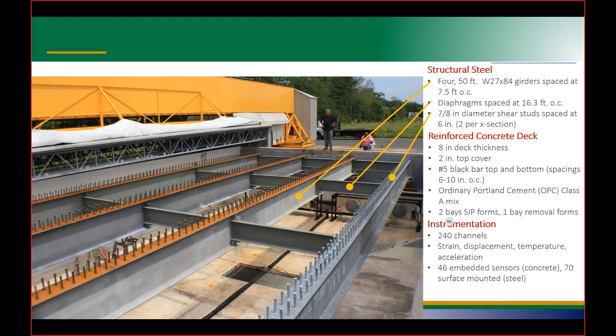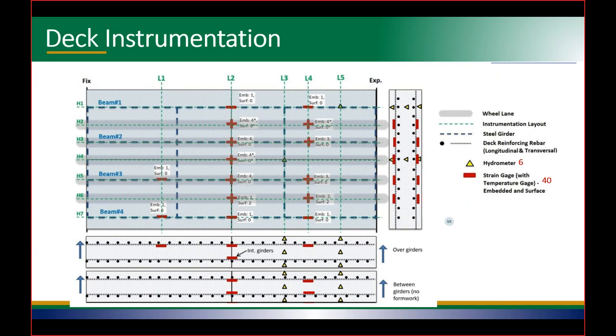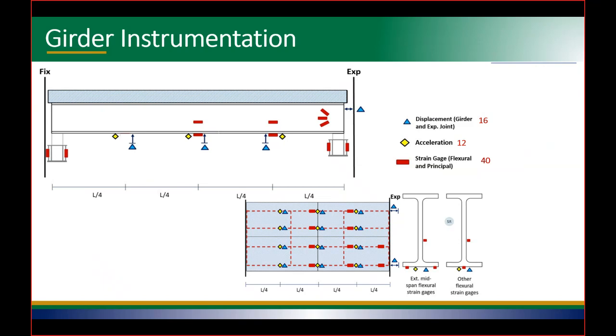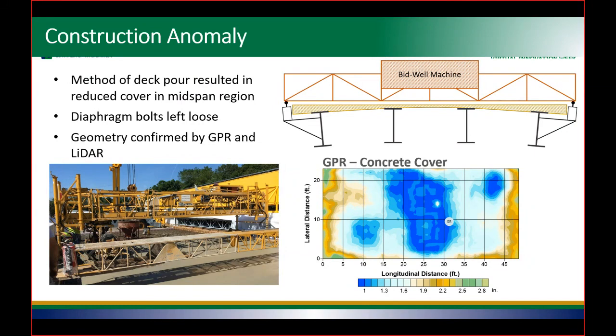We also installed a full fixed instrumentation system. That included 40 strain gauges embedded in the deck. Each strain gauge also included a temperature gauge, a thermistor, and those gauges were tied alongside the longitudinal and transverse rebar and at different depths to provide a full characterization of the strain profile in any given section. The steel girders also had strain gauges, again, to better characterize the cross-sectional strain profile, and also to locate neutral axes. And then we had strain gauge rosettes at the ends of two of the girders to better characterize shear strain, and strain gauges in the pedestals to capture the entire load presented to the structure. And then displacement gauges and acceleration gauges distributed at quarter points to give a full picture of the shape of deformation and motion of the structure under loading. So in total, there are, I think, 120 different sensors.